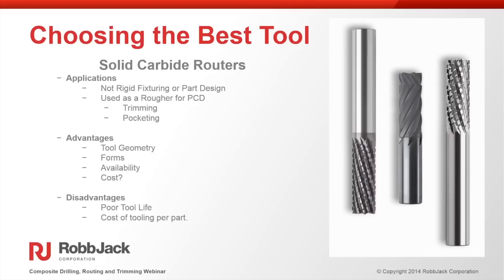When choosing what tools to use for trimming, it's very similar. You have the same type of thing: carbide, diamond coated, and PCD. For trimming applications, carbide is usually used if you have an unrigid machine or poor fixturing, because the cost of the tool is usually a lot less. Some of our customers, if they don't have a very rigid setup and they need to do heavy trimming, might trim with the carbide tool and then come back with a diamond-coated tool or PCD tool just to finish a light cut.